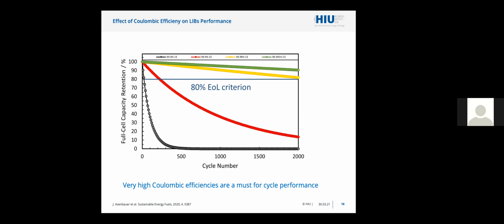You see here that even 99.9% Coulombic efficiency results in a very poor life. Decent Coulombic efficiency starts to be above 99.99%. And in some cases with lithium-ion batteries, even 99.995% is achieved, and this can result in a cell life longer than 2000 cycles. So always keep in mind the extreme importance of Coulombic efficiency, which I think has been highlighted very well by Jeff Dahn with his accurate measurement system.